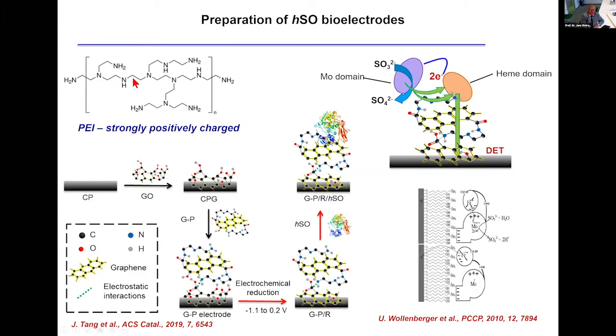Here is a scheme showing how these composite surfaces are prepared. There's this polyethylenimine, strongly positively charged. So what Jing would do is start with the carbon paper, add graphene oxide, and add the PEI. Then she would add another layer of graphene oxide, so that the whole composite would be assembled in this way, and then reduce it electrochemically. The nice thing about it is you can do all your manipulations, all your chemistry, and then reduce and convert it from a more or less insulating to a conducting material. And then you add the enzyme in the end. And here is a cartoon showing what we like to believe is going on. You have catalysis in the molybdenum domain, and then the electron transfer via this whole interface to the electrode.